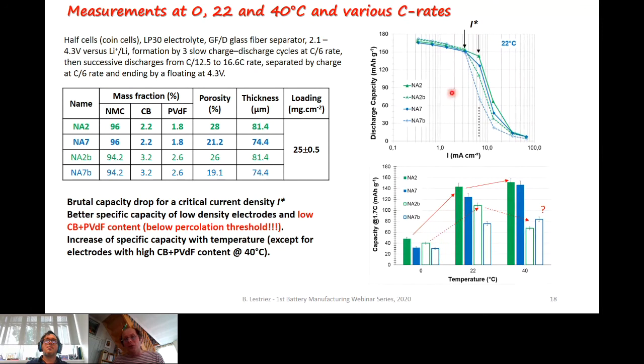And when you look at this region, first, you can observe that it is the electrodes containing less CbP-VDF that are showing the better performance. What I have not shown there, but what we have observed from electrical measurements and also by looking at the percolation of the CbP-VDF domains inside the volumes, is that the electrodes containing less CbP-VDF are not percolated. We are below the percolation threshold. However, they are showing the better performance.